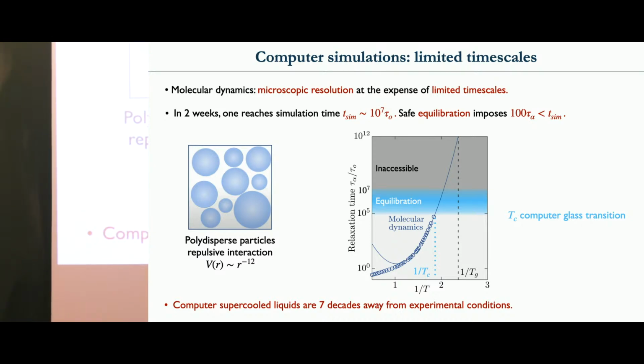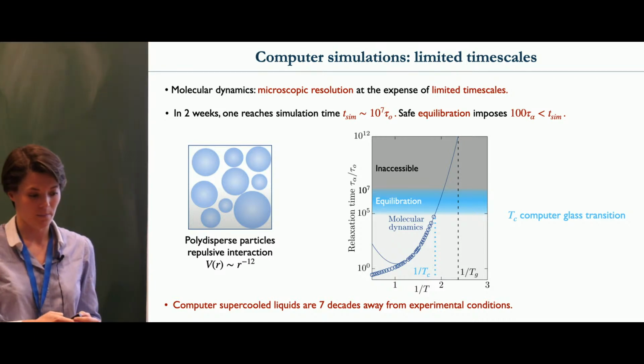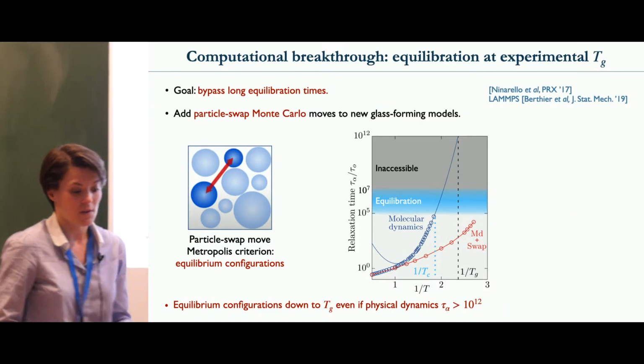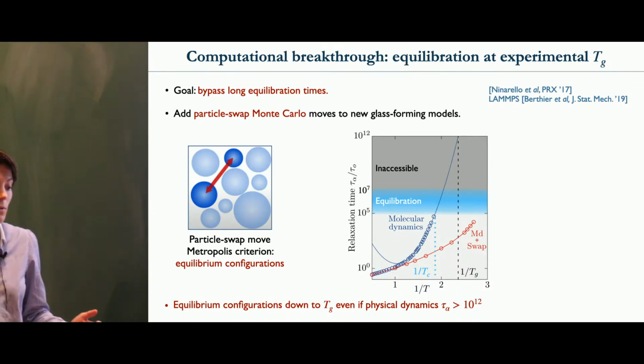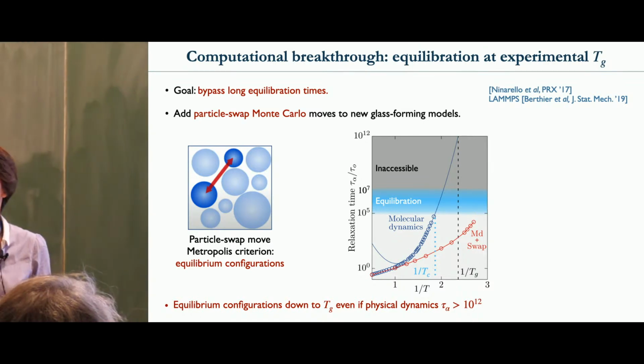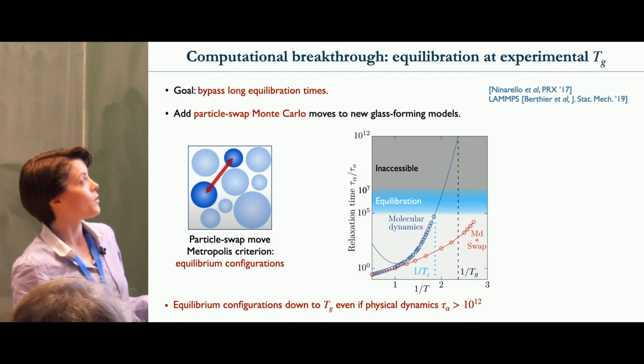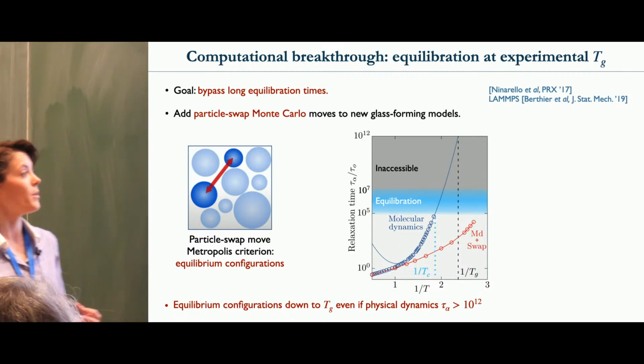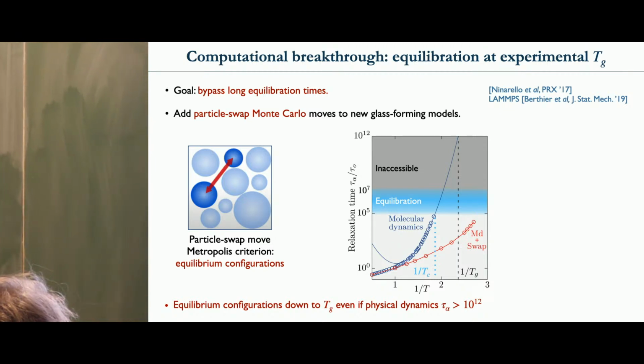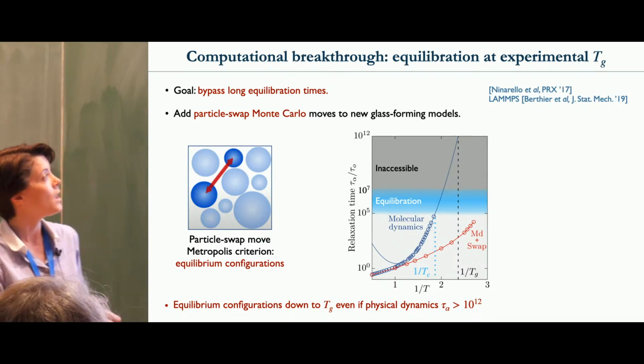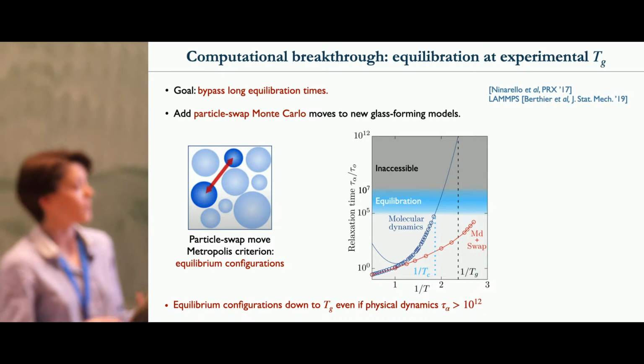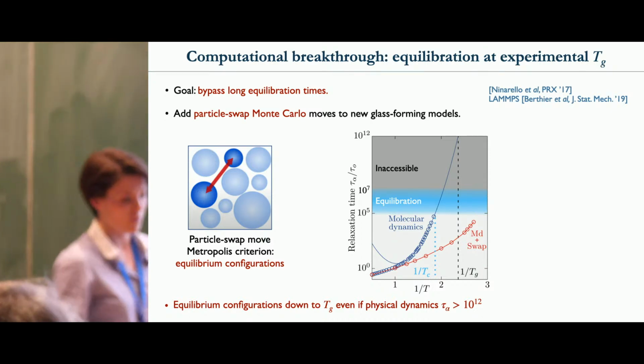And this is really different from the experimental glass transition, which corresponds to the point where if you extrapolate, you would reach 12 decades of slowdown. So very recently, there was this huge breakthrough, I would say, in these computer studies, which correspond to the optimization of the particle swap algorithm. So you probably have heard about it. It was developed in this paper by Ninarello, Berthier, and Coslovich in 2017. And we implemented this in LAMMPS to be able to share it with other users.